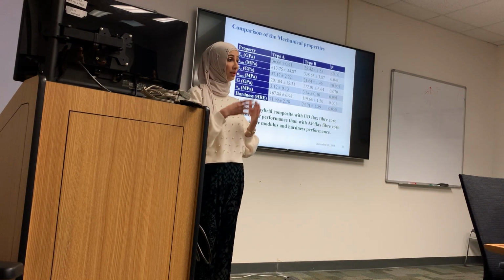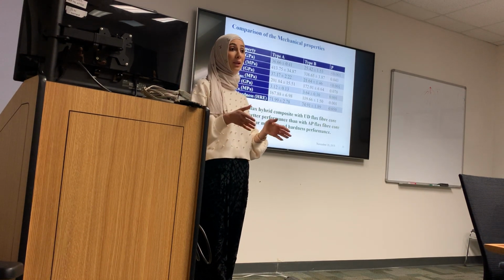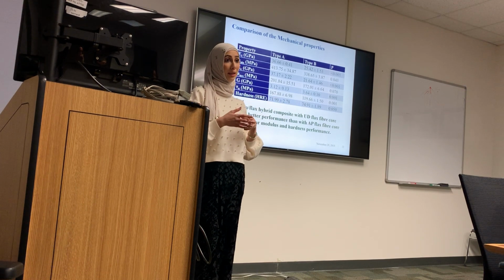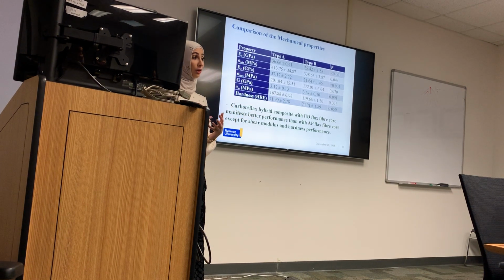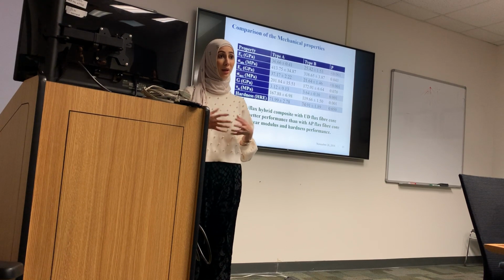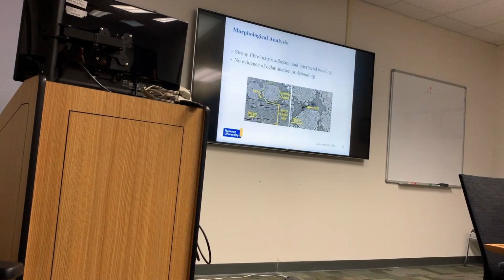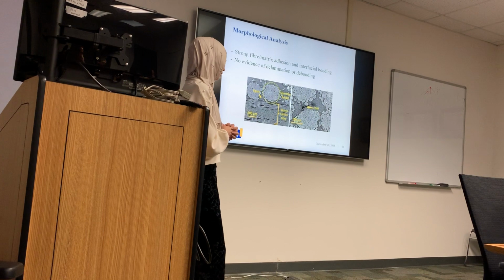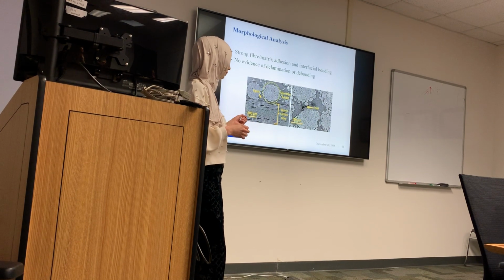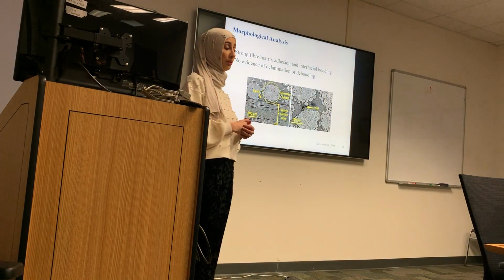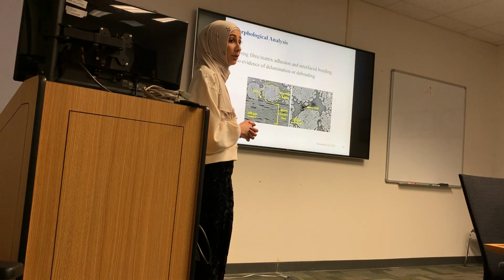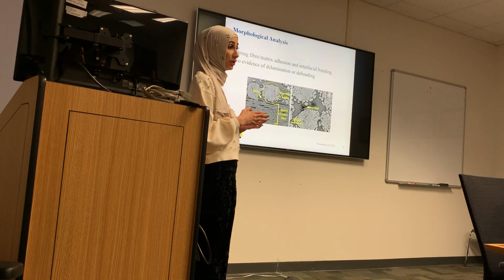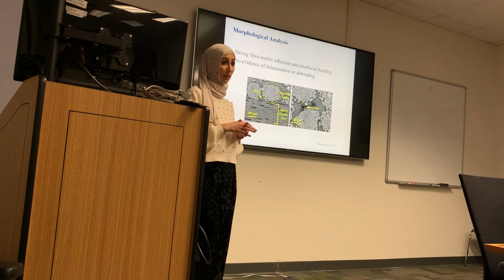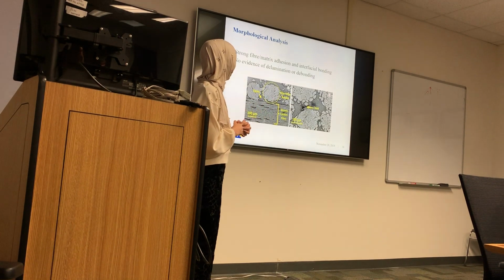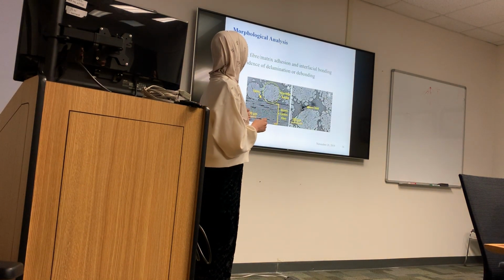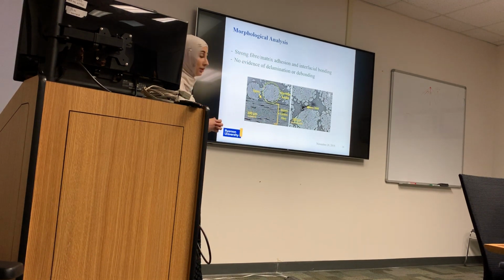That's related to the flax being oriented unidirectionally, aligned with the applied load, which provides high load capacity that restrains crack initiation and propagation. I also performed morphological analysis to see the quality of bonding between fiber and matrix, or fiber to fiber. I've taken 20 to 25 images from different locations of each composite. And we see here that there's good bonding, with no sign of delamination or debonding.